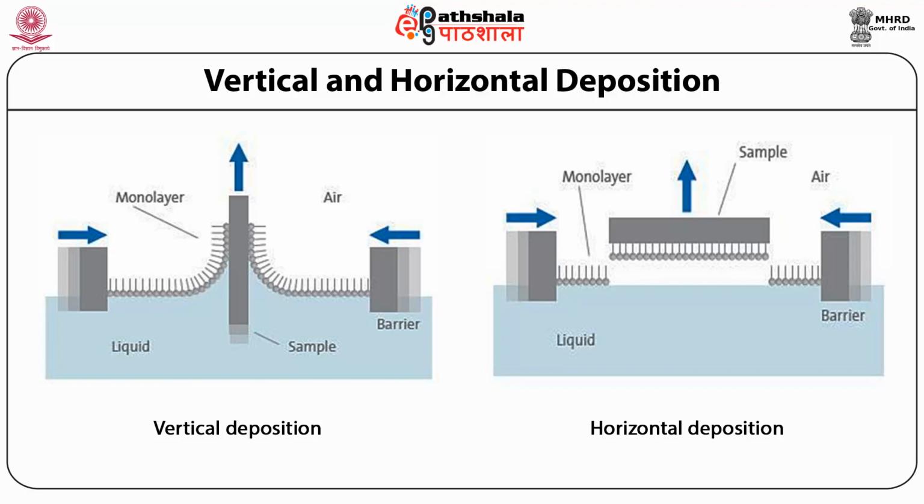On the right hand side you can see that we can also use the deposition technique in a horizontal way. Here we have a hydrophobic surface, and we just bring it close to the layer and touch the water surface from above, and this hydrophobic tail will stick to this hydrophobic surface, and in this way we will get a deposition of a monolayer in a different way.